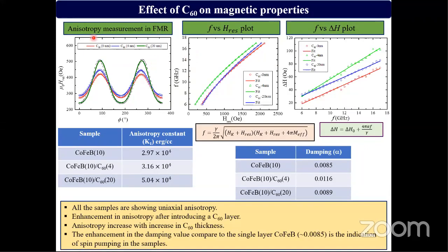To calculate the anisotropy of this system, we have performed angle-dependent ferromagnetic resonance. So this red curve is the single layer cobalt iron boron, and this blue is for cobalt iron boron and C60 4 nanometer, and this green is for cobalt iron boron and C60 20 nanometer. So for this H resonance versus phi plot, we have seen that introducing a C60, the anisotropy is enhanced.